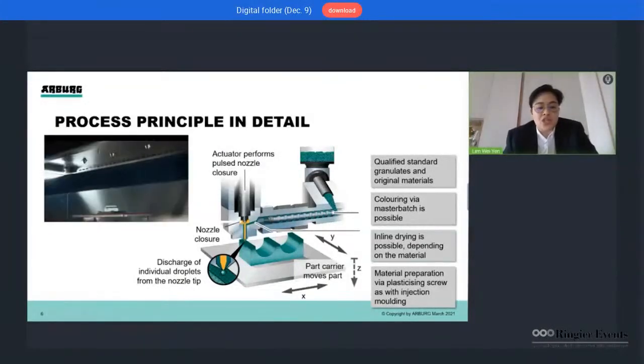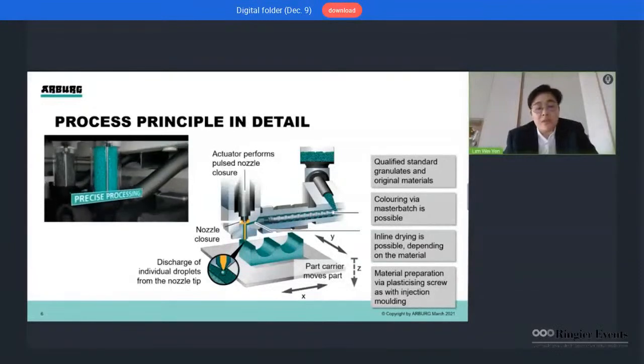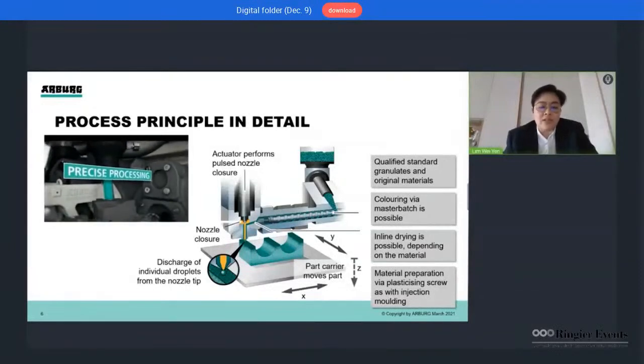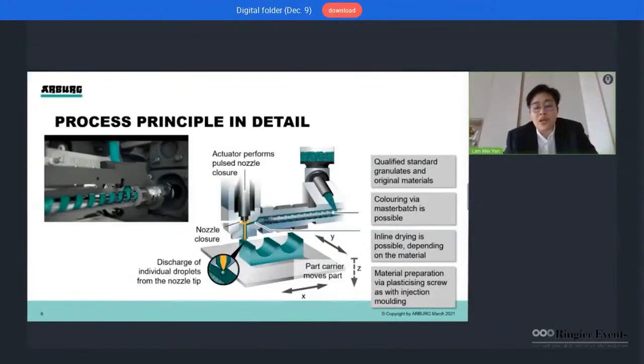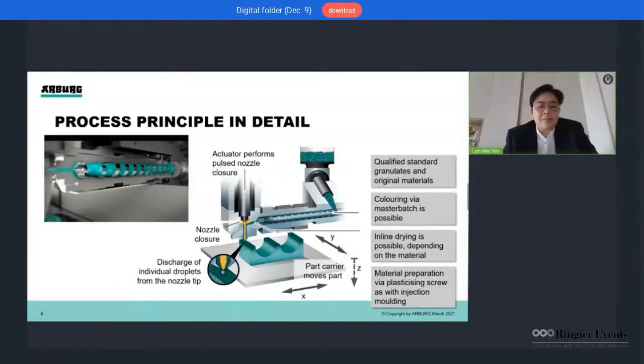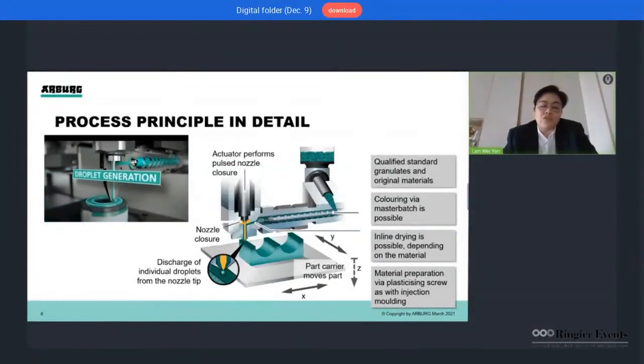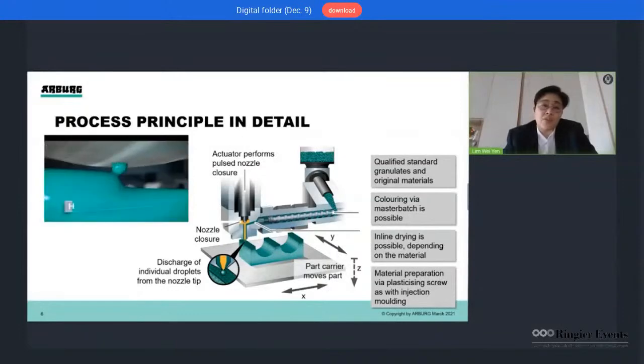The droplet discharge is then synchronized according to the movement of the build platform, resulting in discharge frequencies of up to 300 droplets per second. Typically, the layer thickness that we are able to reach is in the range between 100 microns and 300 microns.